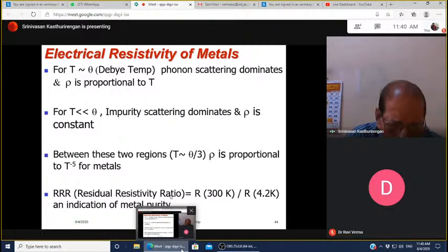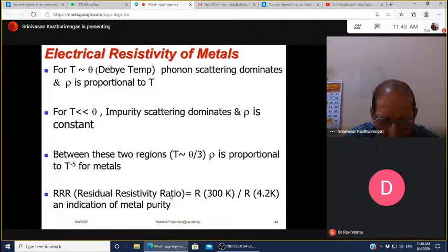Actually, for metals with purity, especially let's say we talk about copper, for example, there is a term introduced called RRR, the residual resistivity ratio, which is the resistance at 300 K divided by the resistance at 4.2 K. It indicates the material purity. So if the number is very large, it means the material is quite pure.